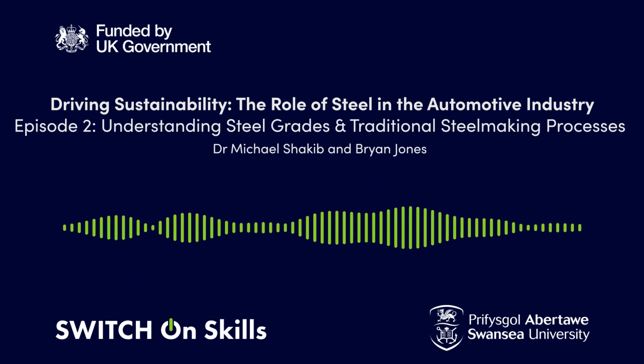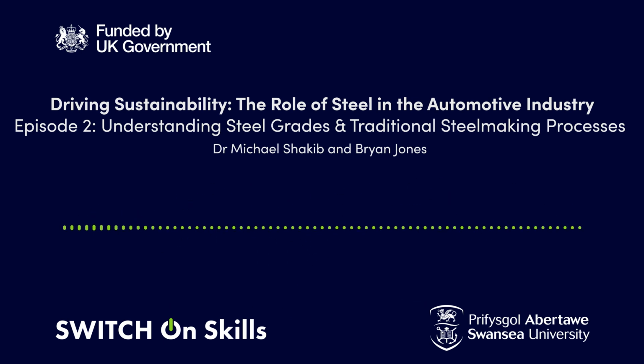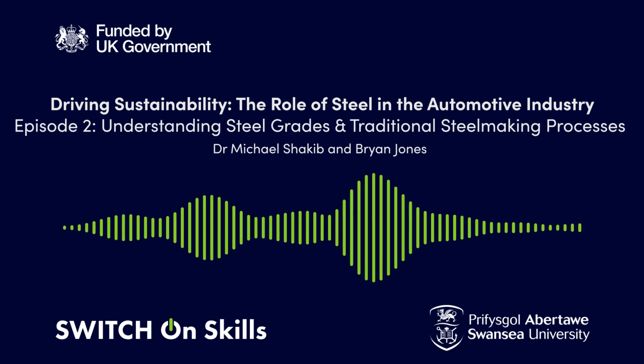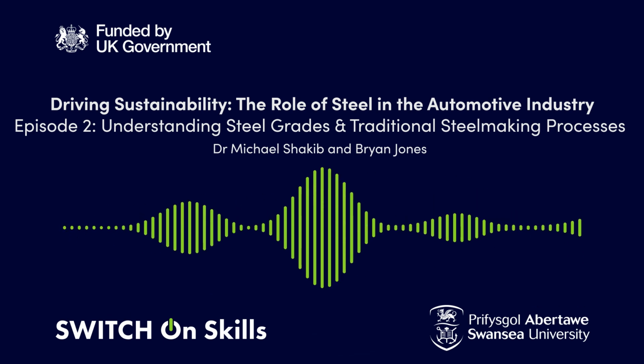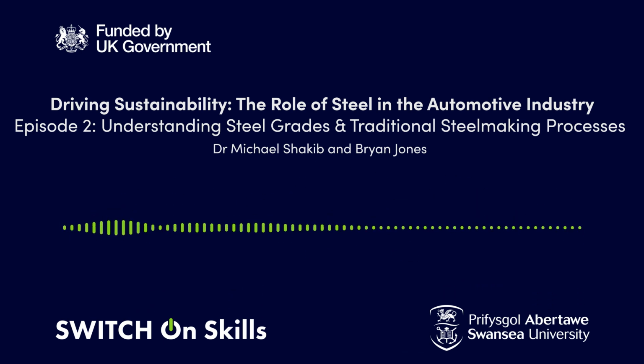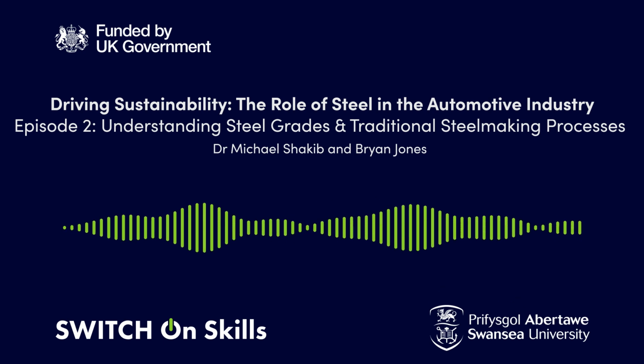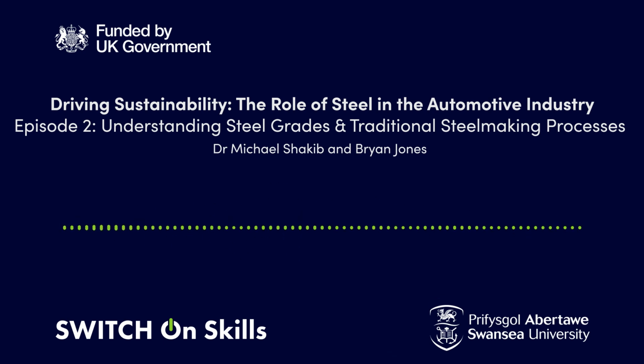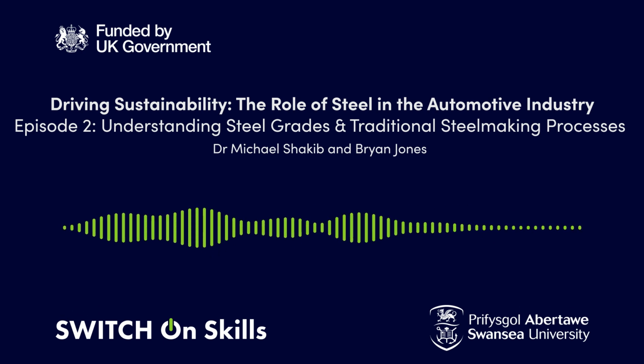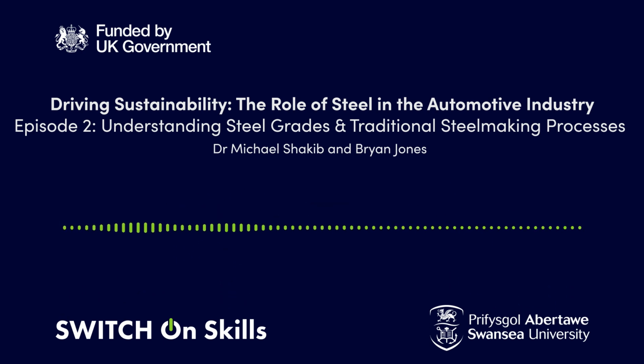So the consequence of that then is you either sort out your scrap. So if you're making a particularly challenging chemical composition, you'd use scrap steel of known composition only. Or alternatively, a product that we haven't discussed as yet is direct reduced iron, which again has a known chemical composition. Tell me about that then, Bryan.